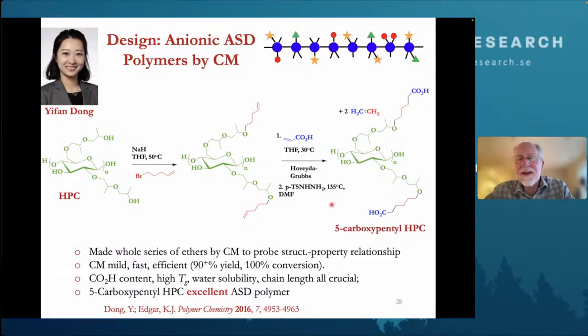And sure enough, this is a grad student's dream reaction. It happens in an hour or so, at close to room temperature. The conversion's 100%, the yield is way up into the 90% range. We hydrogenate that product to make it more stable, and that gives us this carboxypentyl hydroxypropyl cellulose.